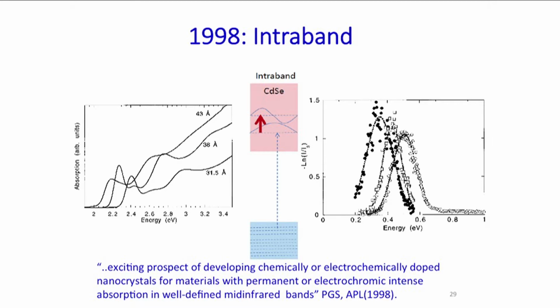So our efforts to move in that direction started actually quite a long time ago, about 15 years ago. And what we did was to take the cadmium selenide, the standard colloidal quantum dot system, and verified that we had indeed strong infrared transition called intraband transition. To observe them, we had to somehow put an electron into the state. That was before we had invented the electron transfer method. So we put the electron into the state, and then by infrared, we were able to probe that this electron was there. So there's a transient pump probe experiment with lasers. And what we could see indeed is this very strong infrared transition where the sample became effectively totally opaque at some specific infrared band after photoexcitation in the visible.